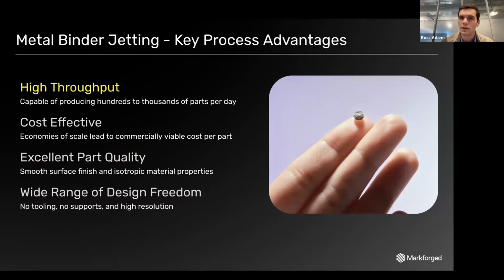Nothing really competes with binder jet in terms of throughput and speed. And the key reason there is that we're using an inkjet print head and the time per layer is constant. Regardless if you have 1 part or 1,000 parts in that cross section, it takes the same amount of time. We don't have to trace it. We don't have to draw the geometry of the part. So we can produce hundreds or even thousands of parts per day, a really efficient process to create green components.